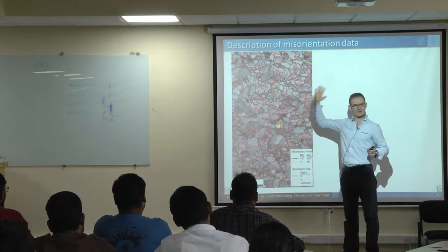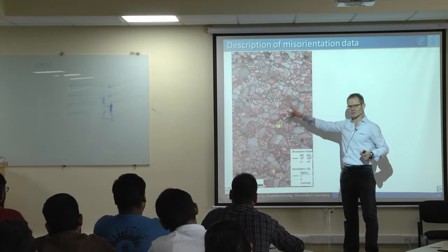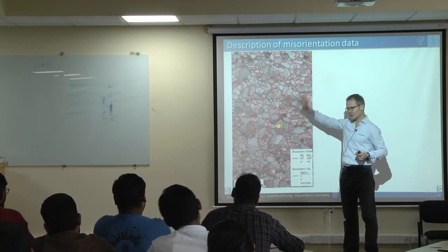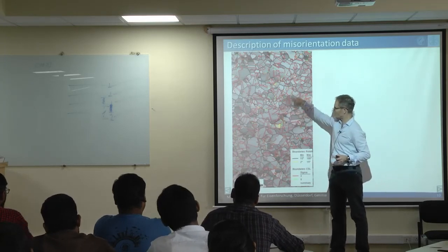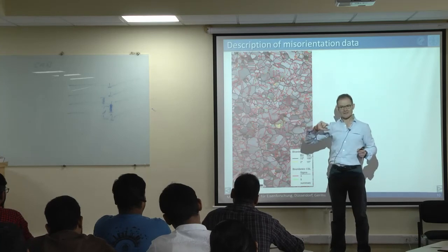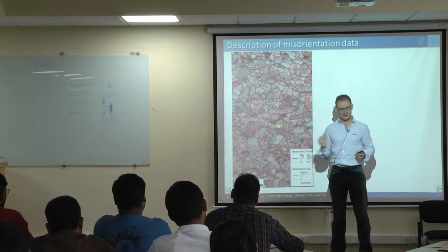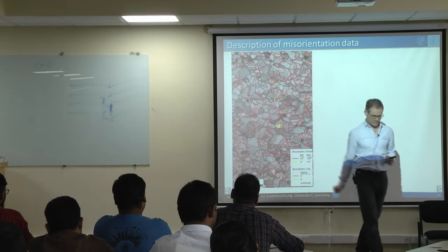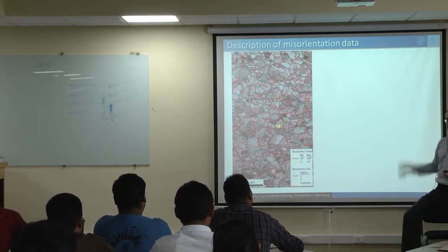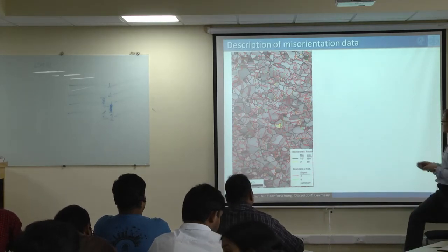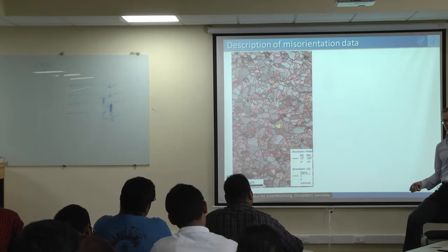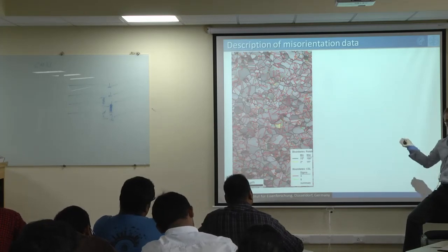So if you now would make an etching experiment or whatever kind of testing of properties, you would find, okay, the coherent twins behave very nicely, but the incoherent twins behave not nicely at all. We have studied a lot of solar cell materials. The twins are no problem for the solar cell behavior at all. That's even not visible.